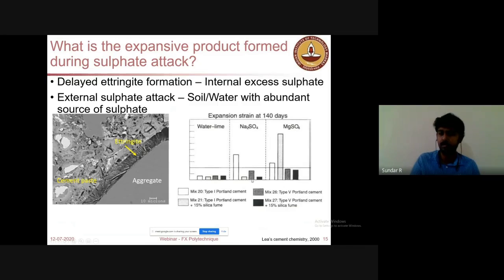So when you add some fly ash or silica fume, you could see there is a reduction in the mass loss or expansion. That means there will be a lesser amount of ettringite formation. So the concrete under sodium sulfate attack will have higher expansion when OPC was used. When there is an addition of SCMs, there is a reduction. Similarly, when magnesium sulfate was used, the concrete with silica fume tends to show very high deterioration because of much smaller pores.